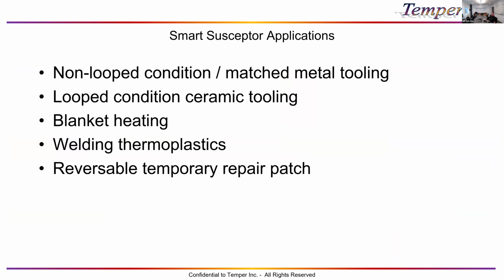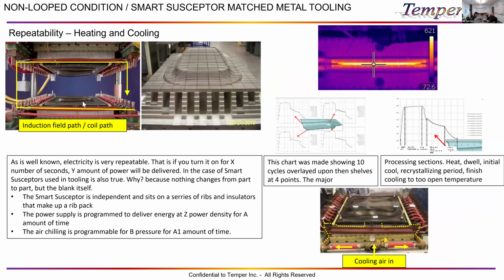So again, we're going to talk about matched metal tooling, ceramic tooling, blanket heating, welding, and this reversible temporary repair patch. So again, if I look at this from the physics standpoint and where we started, you have an induction heating field that is supplied via a coil, and you can see all of the different connectors for the coils here onto a shell, and then the shell heats in under 30 seconds, and you can see that 30 seconds here.